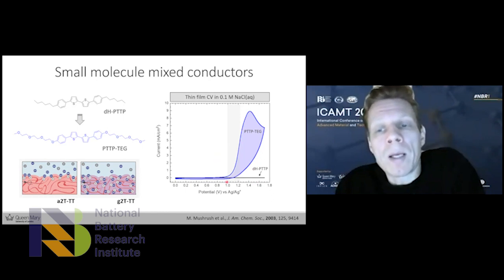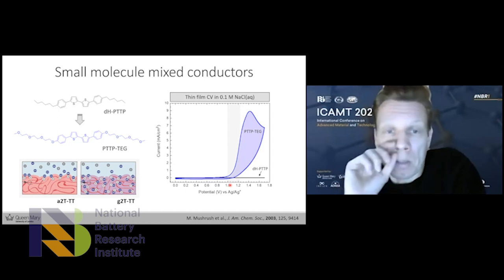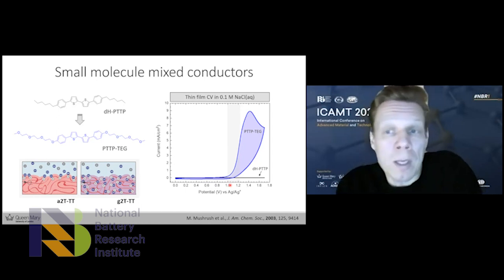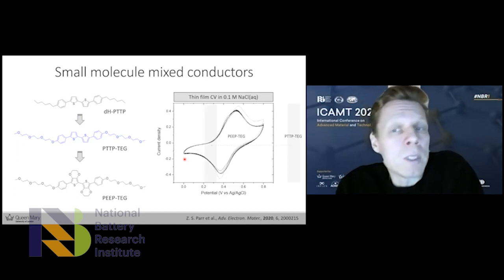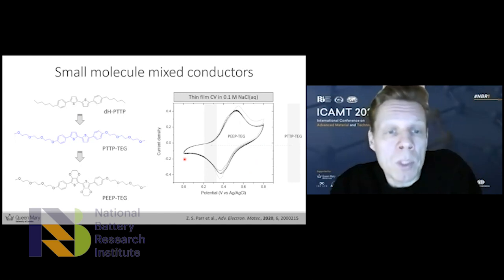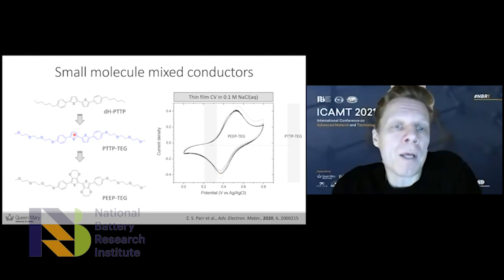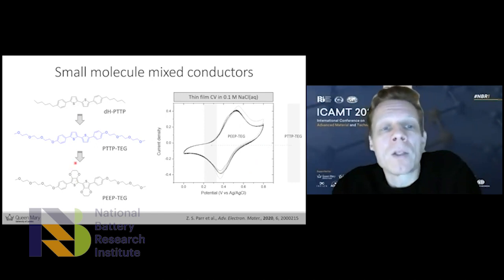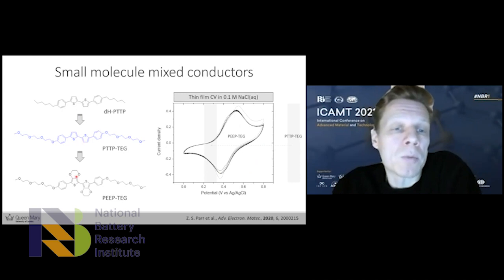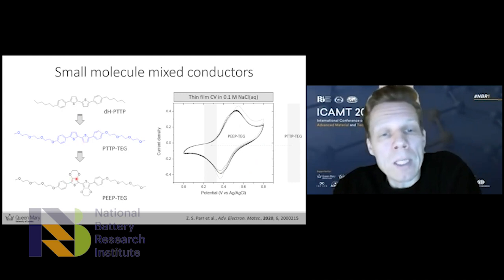Although we still need to apply quite a high bias, you can see the onset of oxidation is above 1 volt, which is quite high, and it's not particularly favorable for organic bioelectronic applications. So the next thing we did from a synthetic point of view was to try and make this material much more electron rich, so we can oxidize it at a lower potential. We decided to modify these two central thiophene units here and turn them into EDOT, this ethylene dioxythiophene unit here. So when you take the two central thiophene units and substitute with a central bis-EDOT unit, you